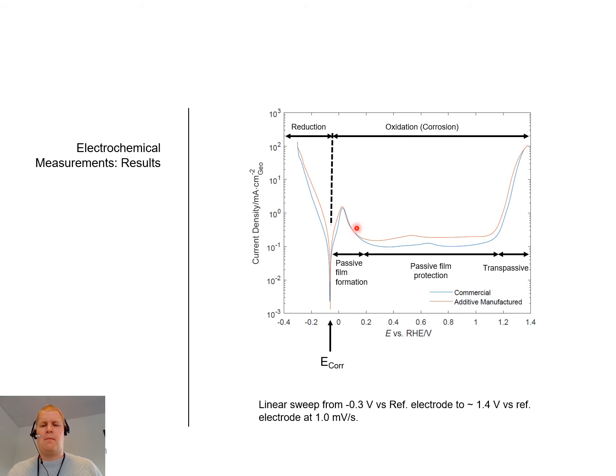You have a peak here, which is believed to be due to the formation of a passive film created on the surface of the sample. This passive film normally keeps the corrosion rate at bay, making sure that the current is primarily constant in this area here. But then when you reach a certain potential, this protective layer tends to crack up, and then you have a rapid increase in the corrosion rate.